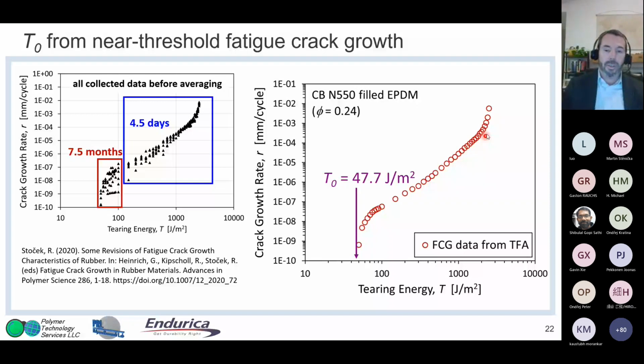And Radek actually saw the downturn and measured down to below 10 to the minus ninth to allow the determination of a T0. And he found a value of 47.7 for this carbon black filled EPDM. We'll compare this value to the cutting method later. But you can see, yeah, crack growth testing, you can get most of the information for the curve in a few days. But if you want to get anywhere close to the fatigue threshold in order to quantify it, then it starts taking really extremely high lab times.